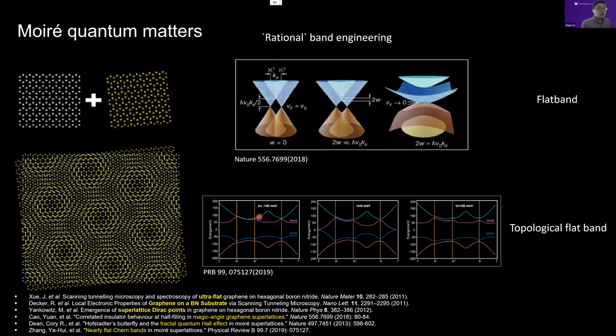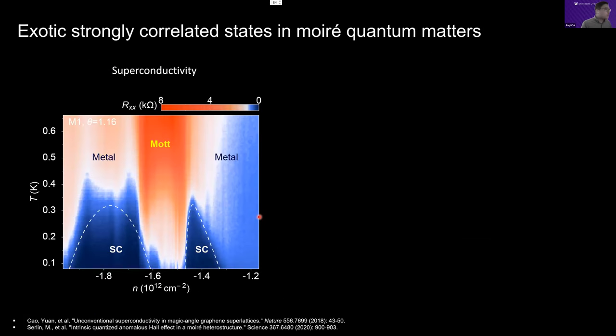Okay, so experiment actually followed up very quickly with the surprising discovery of superconductivity in this marginally twisted graphene bilayer. So what you can see is that if you hole dope the system to the so-called integer filling of the moiré, which is you put one hole per moiré superlattice unit cell, that can be reached by, for example, a single back gate or top gate, okay? And then you dope carriers into the system. It should be a conductor according to band structure calculation.